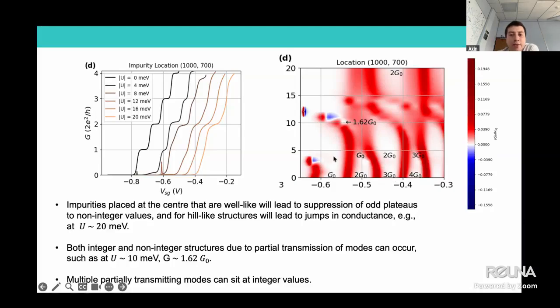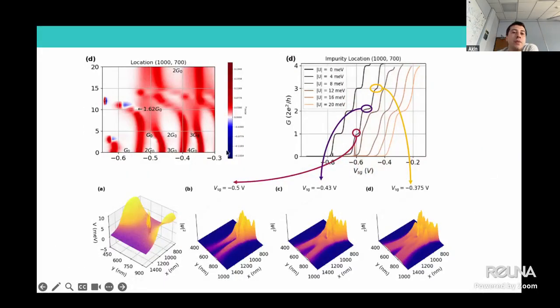And when we increase the impurity range, the first plateau actually corresponds to the second plateau in the non-impurity case. So here you can see an image of the wave function inside the channel. When we look at that first plateau at that split gate voltage, we actually see two modes partially transmitting in the system. And this partial transmission is quite important because if you don't have a shot noise measurement, then you wouldn't be able to separate whether there are two modes in the system or not.